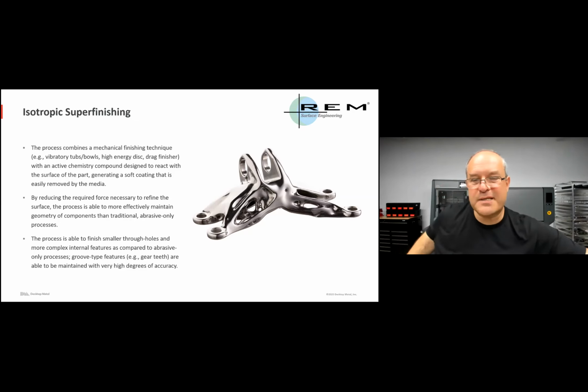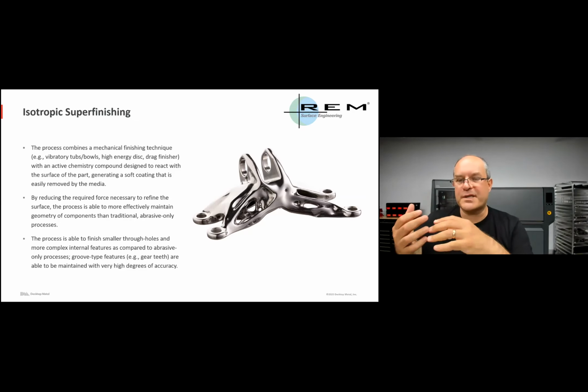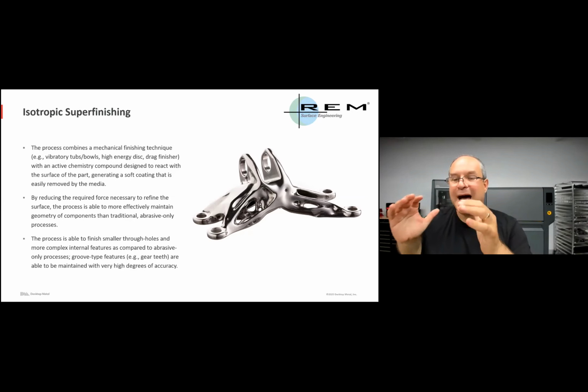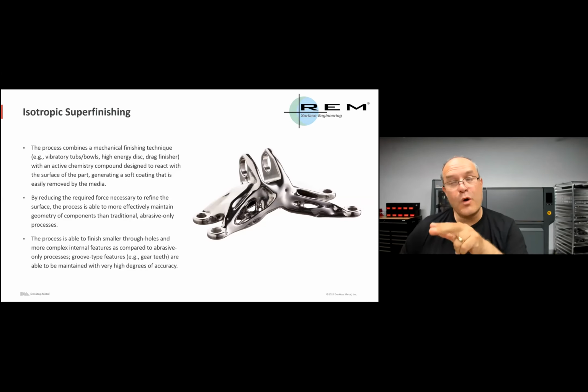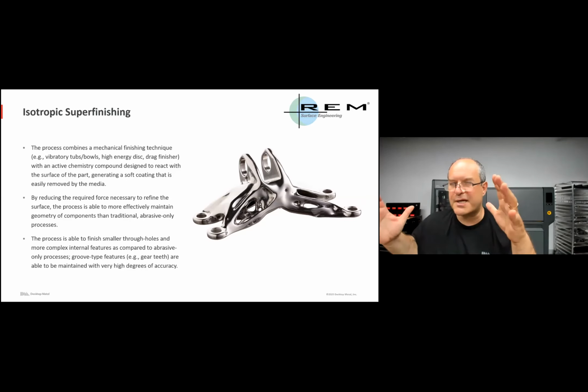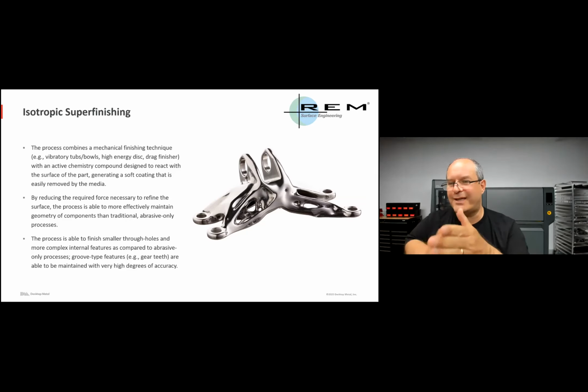We'll see on the next slide exactly how it works. But this is a way to reduce the forces necessary to get that smoothness, while still not removing a lot of material. And so you maintain the geometry that you printed, but you still wind up with a very smooth surface. With the previous processes, if you wanted to get a very smooth surface, you'd wind up removing possibly half a millimeter or a millimeter or even more off the surface. So your part starts to change geometrically. Here, you're removing much less, yet still achieving this kind of finish.